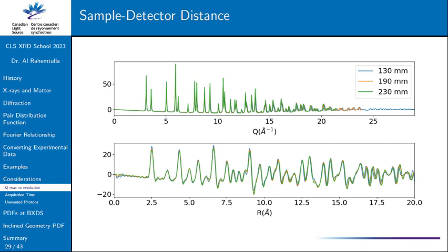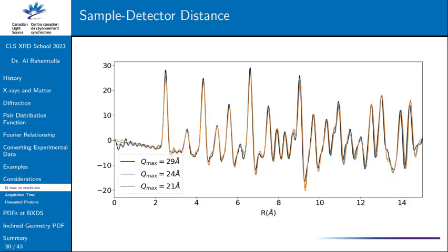We can kind of see this over here when we just vary sample detector distance, where we go out certain distances, but we'll start seeing that when we go further in Q, we get sharper nearest neighbor peaks. But as we go further out to larger radii, now the effects of our Q resolution being dampened because we have finite pixels in our detector means that our long range ordering is being compromised. And we can see this a little better here in just this little zoom in, particularly here in the orange and the black at these two different extremes.